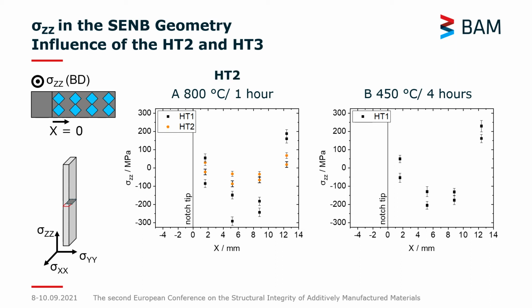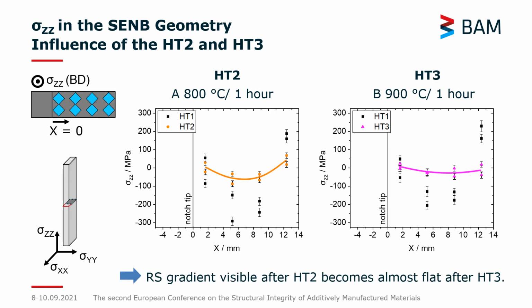We still see that there's a profile in the residual stresses along the remaining ligaments in our specimen. And if we apply 900 degrees, this gradient is almost not visible. So there are two things to note: the reduction in the magnitudes and a flat profile when applying 900 degrees. And in fact, when we think about macroscopic residual stresses that need to balance by definition over the component scale, a flat gradient is in essence an indication for almost fully relaxed residual stresses.